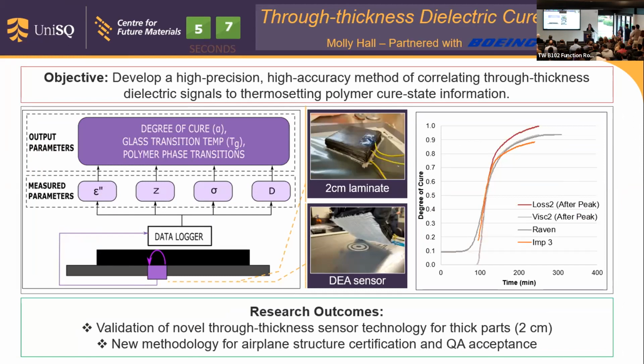Hello, my name is Molly, and I'm researching dielectric cure monitoring methods for thermoset composites. For this, I am working on a precise and accurate method of correlating the dielectric parameters to the polymerization reaction of an epoxy carbon fiber composite that's about 2 centimeters thick. This addresses two of the main challenges we have within aerospace process monitoring: we're either monitoring indirectly, looking at temperature, which doesn't necessarily relate to material property development, or we're only monitoring at one specific plane of measurement and we're neglecting what's going on through the thickness of the part.